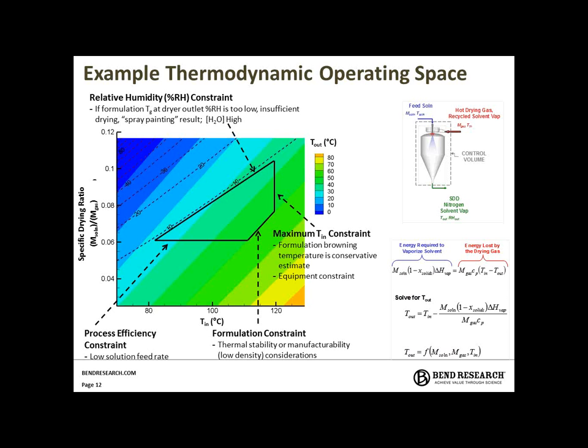Both of these can be identified or solved through that offline thermal gradient strip shown in the previous slide. And the final constraint could be a relative humidity constraint. So you see it follows that 10% humidity line there. And this should be if the formulation glass transition temperature is too low such that the particles don't actually dry down to a solid particle and thus have yield issues, or even more simply, it could just be a water content issue such that if you're above 10%, the water content is too high in the final dried particle exiting the spray drying unit.